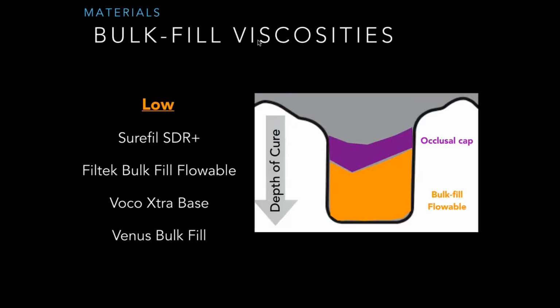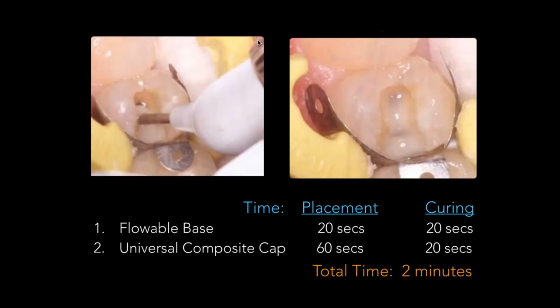They work very well. The big key, I think, to working with a bulk fill is not violating that first increment. You need to know if it says 4 millimeters, then keep it at a 4 millimeter level in placement. Don't violate that placement increment, because then you're going to violate the curability, the depth and the recommendation. That can ultimately fail that restoration's foundation, like we talked about.